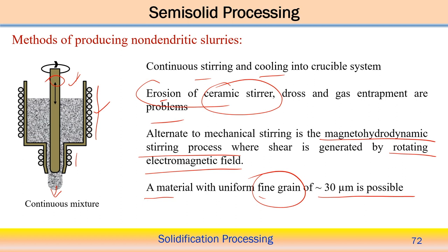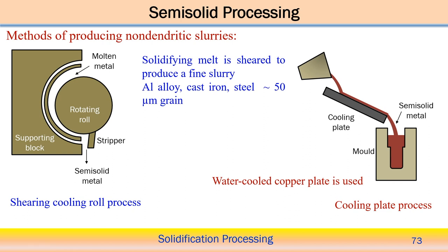So it is understood that semi-solid processing is a hybrid process, casting and forging. When liquid metal turns to solid during solidification in the conventional process, we can use some kind of mechanical shearing action on the liquid metal. At the same time we allow the cooling, and finally the structure will reach a more or less uniform grain structure. That is the main advantage and objective of developing semi-solid processing compared to the conventional casting process, where conventional solidification occurs. That solidification can be modified into semi-solid processing to achieve the objective of uniform grains, and even very fine grains are possible to produce.